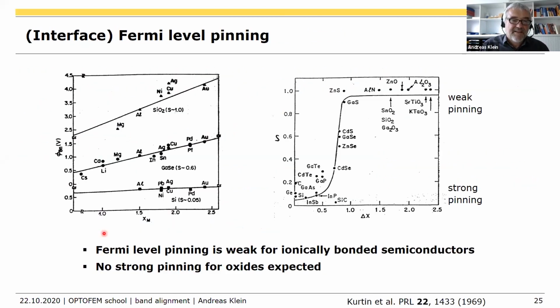This Fermi level pinning by the induced gap states is a slope parameter. So here you see not the work function, but the electronegativity of the metal, which is related. You see for silicon, you don't get much variation. For silicon dioxide, you get a lot of variation of the Schottky barrier with the work function of the metal. That's quite an old work, but people have realized that the covalent semiconductors show stronger Fermi level pinning than the more ionic ones. And I gave you a qualitative explanation for that, which was that these materials have smaller band gaps than these ones. So the density of induced interface states is higher in this case. So we have strong pinning and weak pinning.